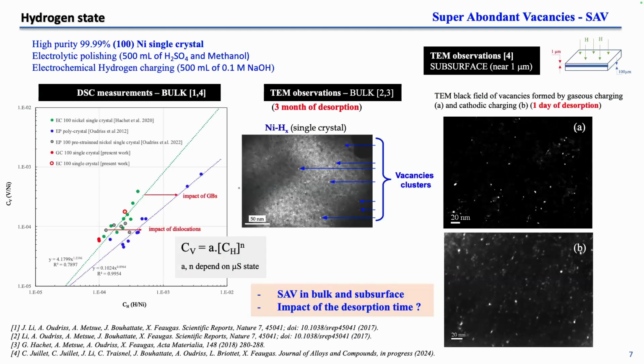To summarize our observations of vacancies, it's important to show the nice relation between the concentration of vacancies and the concentration of hydrogen, which is quite linear in the domain explored. This curve is for a pure single crystal. When we impose dislocations by straining this single crystal, we have a shift of this curve. And when we measure the concentration of vacancies in a polycrystalline material, we also have a shift, which means that the pre-straining and the initial density of defects impact this relation.